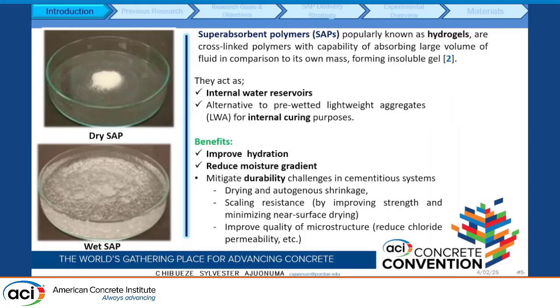Just a little overview of superabsorbent polymers. They are also known as SAPs, or hydrogels. They are cross-linked polymers which have the capacity to absorb a large volume of fluid in comparison with their own mass, forming insoluble hydrogels. They act as internal reservoirs in the concrete, and they can also be an alternative to pre-wetted lightweight aggregate for internal curing purposes.